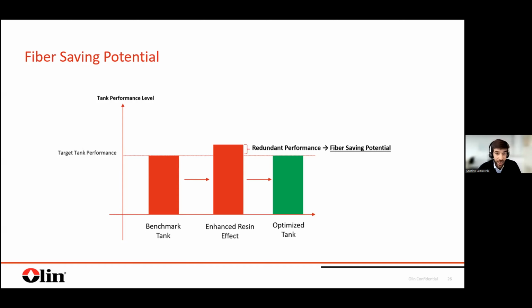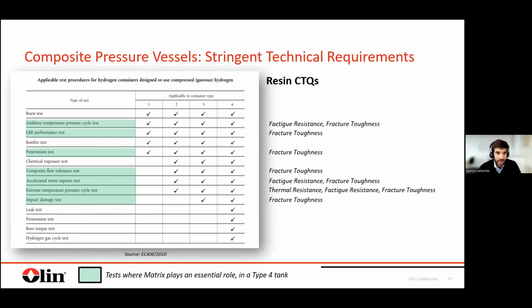And in the next slide, I'm trying to wrap up this first section, just saying, hey, when designing a tank, when maybe trying to optimize the fiber content of a tank, don't think of the epoxy resin, the matrix, as just a glue for the fibers. And here we come to our title: that's something more. The epoxy matrix and the right choice of the epoxy matrix can play a vital role in pass-failing at least 50% of the tests that are needed in a hydrogen homologation test. So we are here to support, and are very happy to support, anyone who needs help selecting the right system for the right application. However, this is not the end of the story.